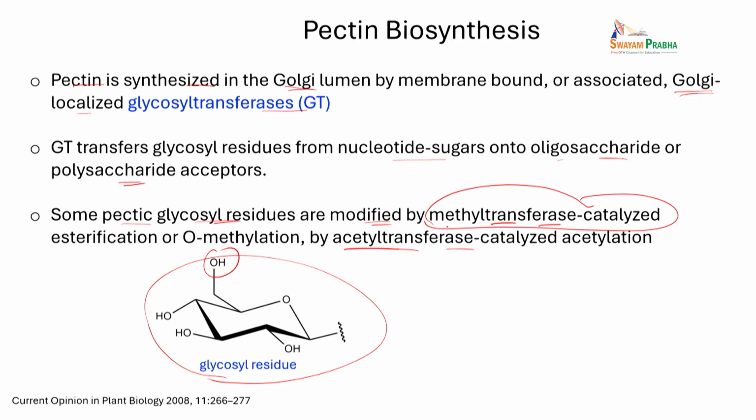So one way to look at this is, can you come up with programmed enzyme combinations that will take sugar and convert it into oligomers and polymers in controlled conditions, so that you can precisely control the type of sugar. If you want to build only homogalacturonan, you can do that, or if you want to change the degree of esterification, you can change the amount of the methyl transferase. If you want to acetylate the polymer, you can also control the amount of acetyl transferase reactions. Okay, so this seems to be one area, again, a lot of possibilities awaiting.